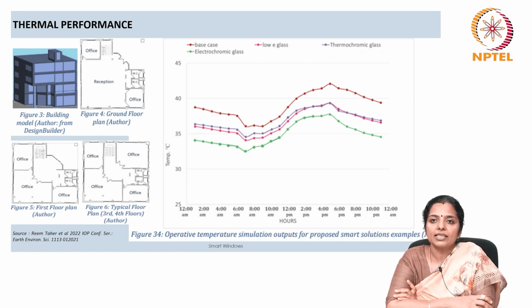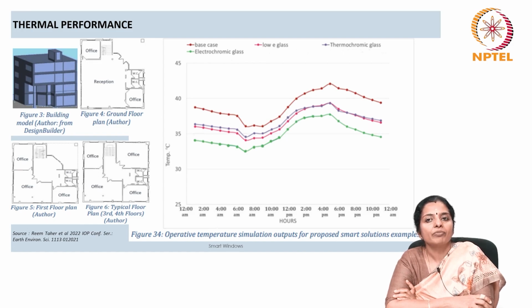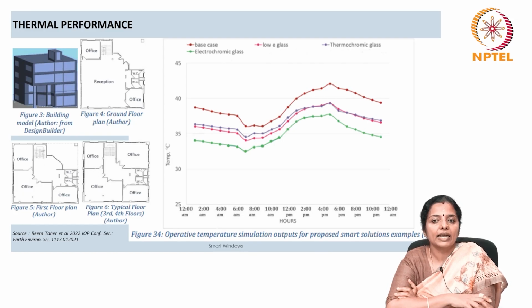Energy analysis indicates that incorporating split air conditioning units alongside the proposed smart glass solutions leads to cooling energy consumption reductions ranging from 21 to 36.4% depending on the smart glass solution type simulated. Thermochromic glazing demonstrates the most substantial energy savings at approximately 36.4%. Despite electrochromic glazing's superior thermal performance, it still achieves a noteworthy 21% reduction in energy consumption, recognizing its reliance on electricity.